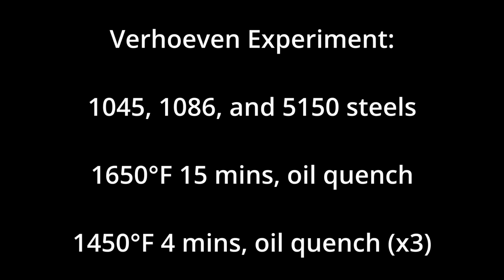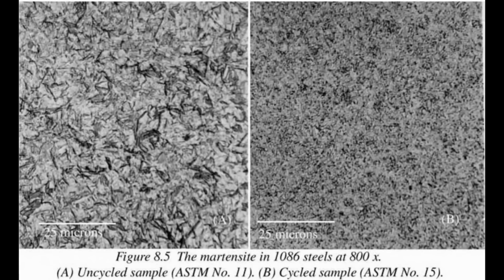I would be interested to see how fine you get the grain size by only 1 or 2 cycles rather than all 3. Or maybe you could just anneal the steel and then heat treat it from 1450 and get the same grain size. Those would all be interesting experiments. But you can't look at his experiment just on its face and say, oh, a triple quench leads to finer grain size, because it's starting from a larger grain size to begin with and seeing if lower temperature cycling can decrease the grain size. And of course it can.